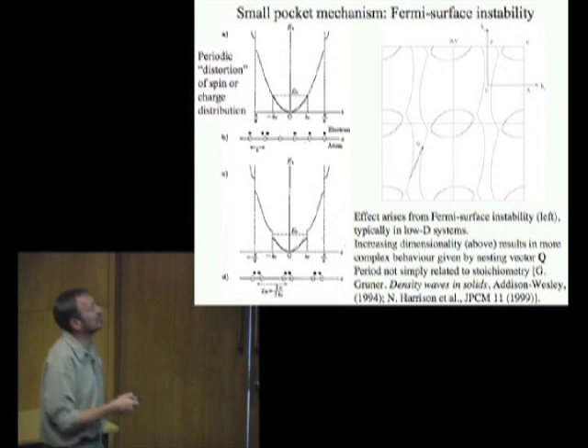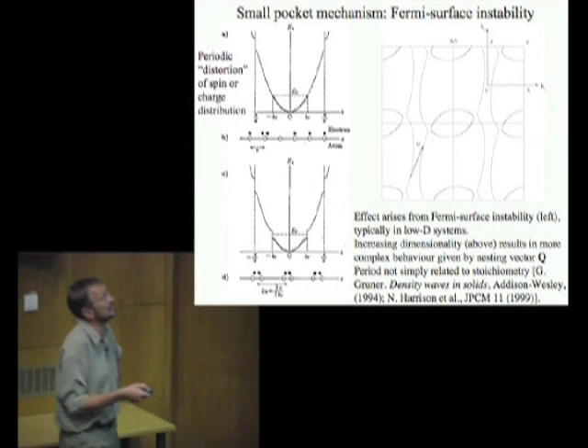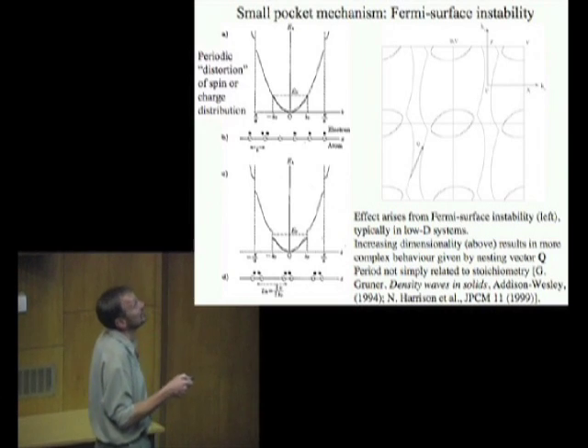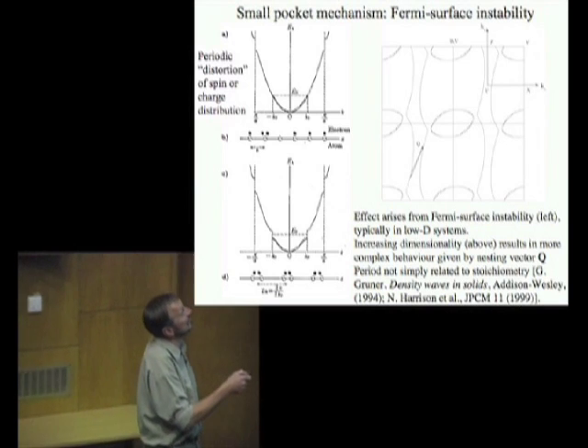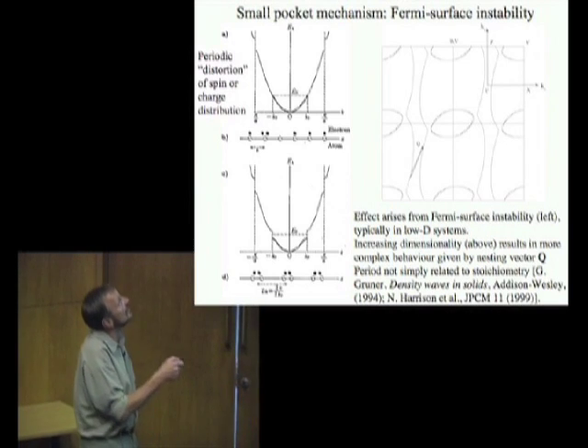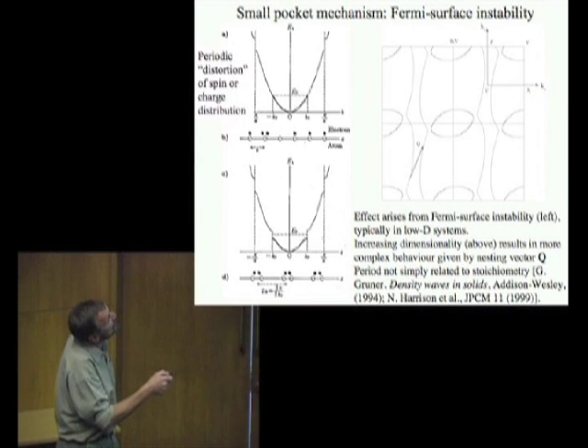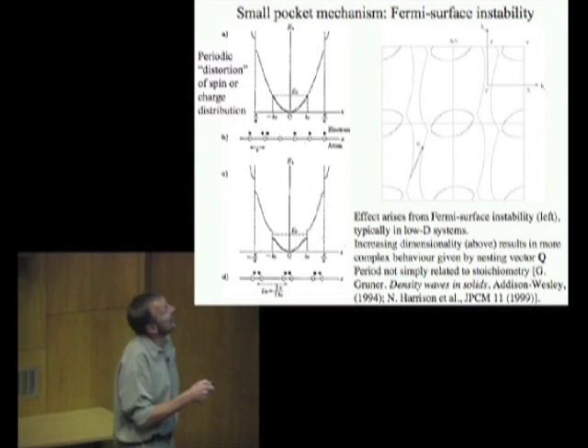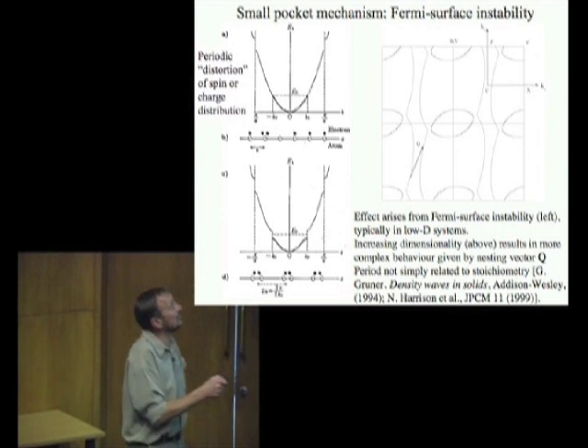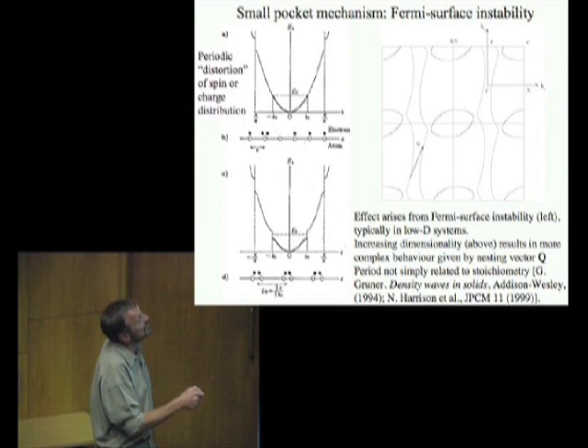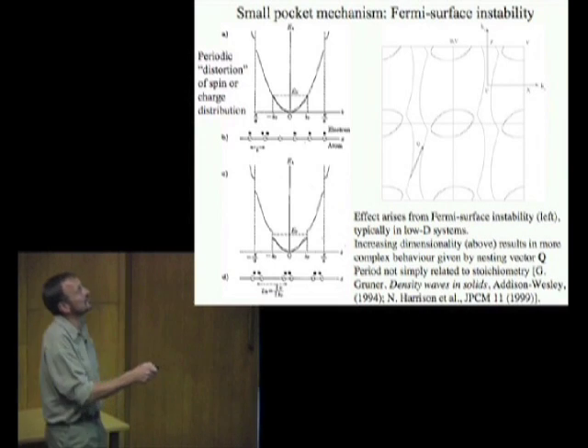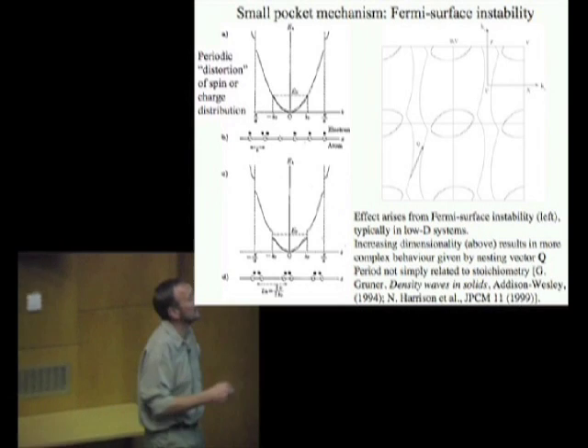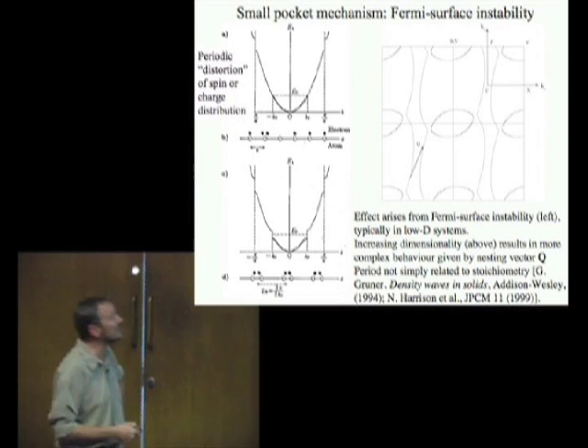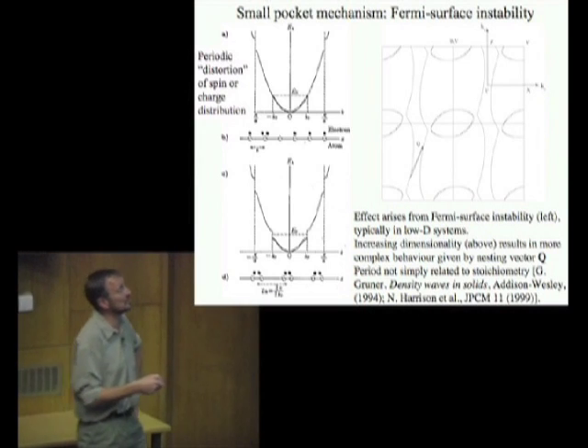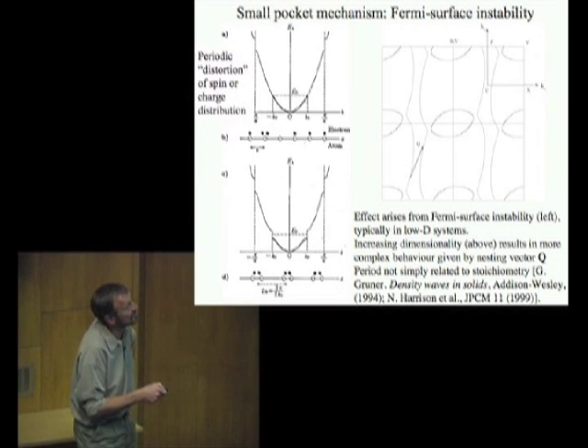Well, here's a very simple example of the sort of thing that drives these sorts of transitions. A Fermi surface instability. This is a one-dimensional system that I've pictured here, just to make things very, very easy. On the left-hand side, we've got our simple band here, like this. And here is the Fermi energy. This is a so-called half-filled band because there's one electron, the black blobs, per atom, which are the white blobs here. And the electrons are happily moving around in this band. Now, it actually happens that the system can lower its energy quite significantly by distorting itself. Now, this doesn't have to be a structural distortion like the one I've shown here, but let's take this simple example for the time being.